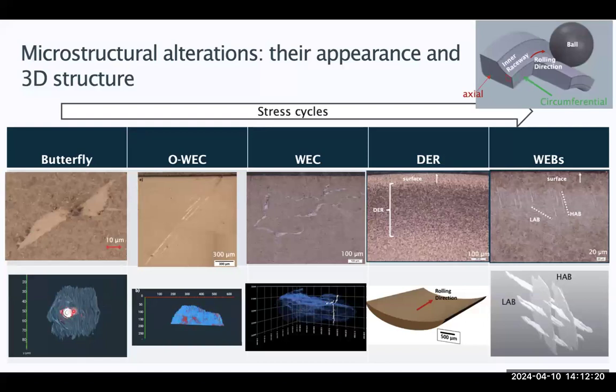It's a very similar structure to this, but we're only showing one slice of that feature. You can see that the blue shows the white area and the red shows the voids. We weren't able to capture an inclusion in this, but we assume there will be inclusions in the orientated white-etching cracks. This is just to show that in 3 dimensions, they could be totally different from the 2D that most people have been looking at.